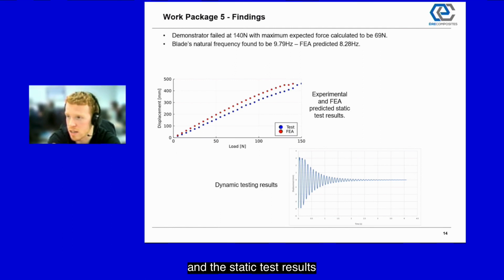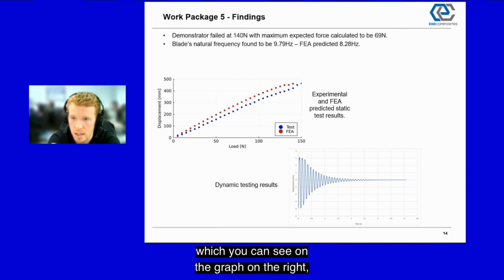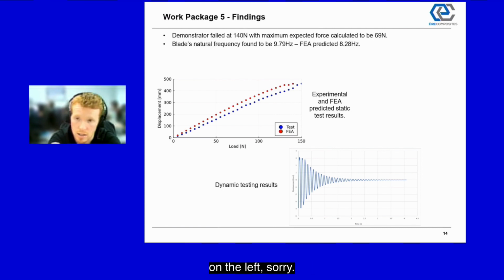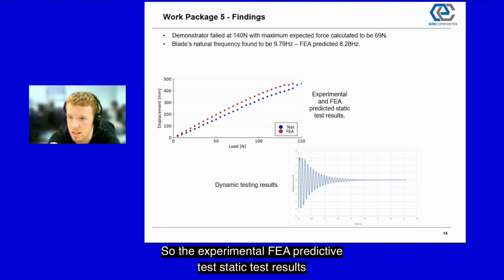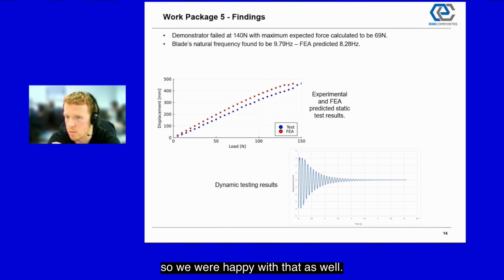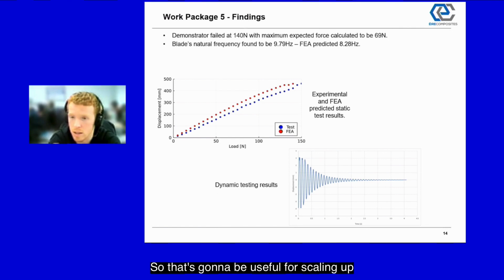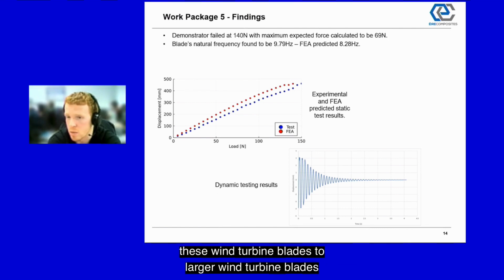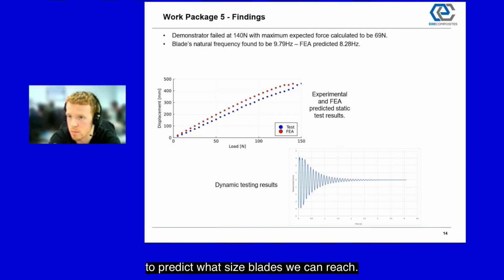And the static test results gathered in the experimental testing match those of the FEA simulation as well, which you can see in the graph on the right, or on the left, sorry. So the experimental and FEA predicted static test results are in good correlation. So we were happy with that as well. That's going to be useful for scaling up these wind turbine blades to larger wind turbine blades, and hopefully we can rely on the FEA results to predict what size blades we can reach.